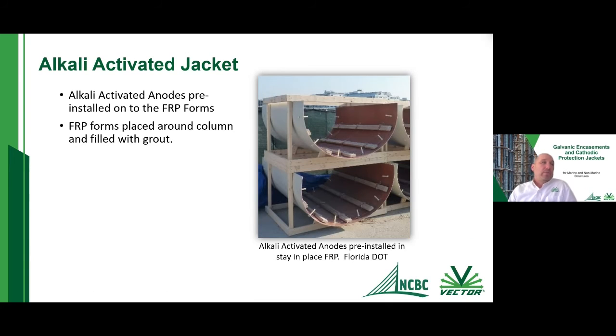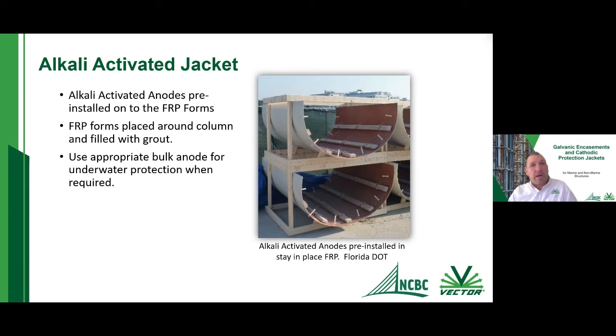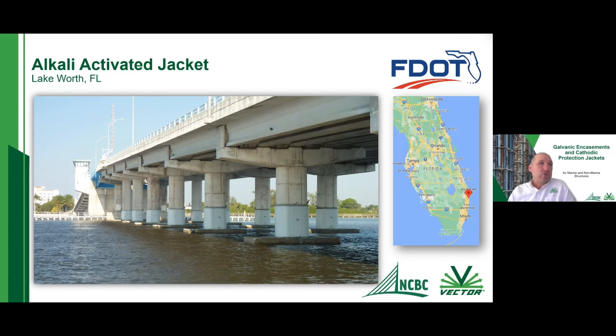So I'm just going to go through a few pictures of the installation of the system. Again, it's going to be very similar to the Tidal Plus system, except that it's not going to actually be in the water. In this example here on the right side, you can see there are some fiberglass forms. There are some alkali activated anodes that are attached to this fiberglass stay-in-place form. This was actually for an FDOT project used just on the north side of Miami. Again, if you're using this in conjunction with a Tidal Plus jacket, or you were bringing this down to the water line, say for a brackish water environment, you'd still want to use an appropriate bulk anode if needed. Here's the structure.